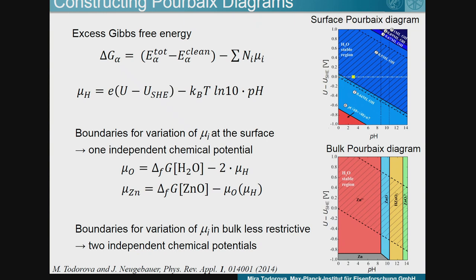And we use our derivations, in which we show that the hydrogen chemical potential can be expressed as a function of the electrode potential and the pH scale, in order to make a transformation and end up with the Pourbaix diagram. So a Pourbaix diagram is an electrochemical diagram in which one sees on one axis the electrode potential change with respect to the standard hydrogen electrode, which is the reference used in experiments, and on the other axis we have the pH scale. Each of the areas that you see here corresponds to the stability of one phase.